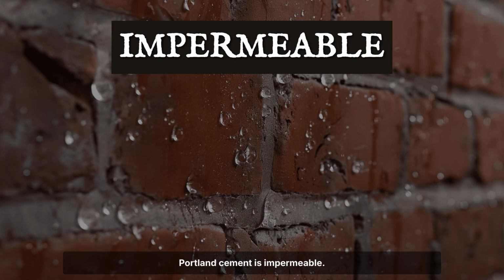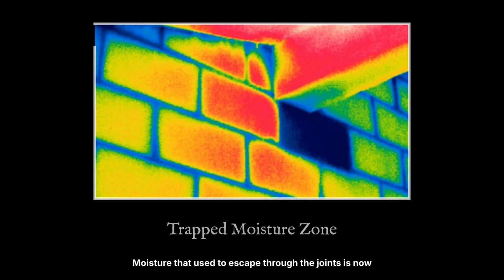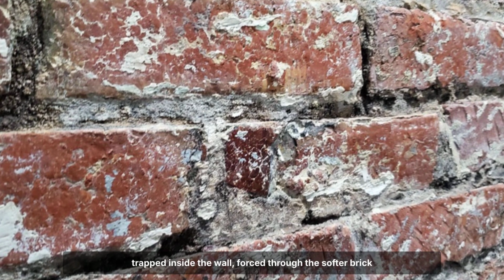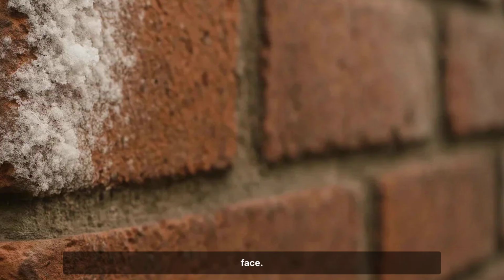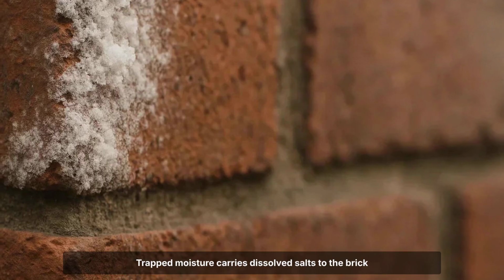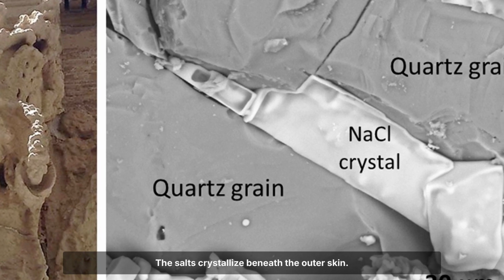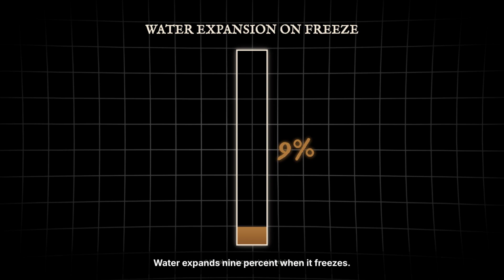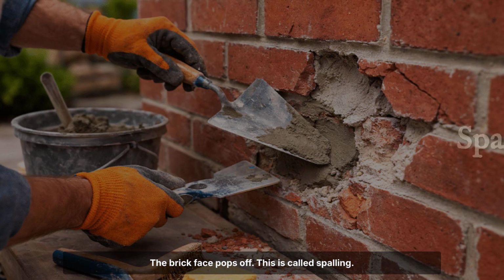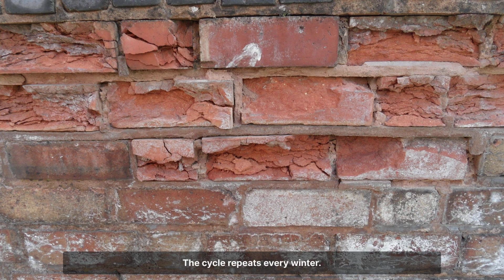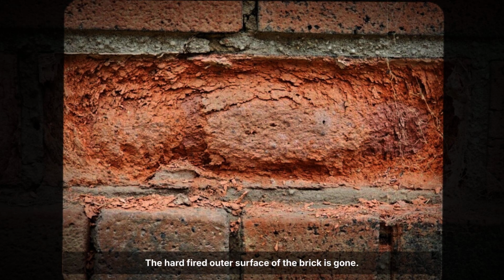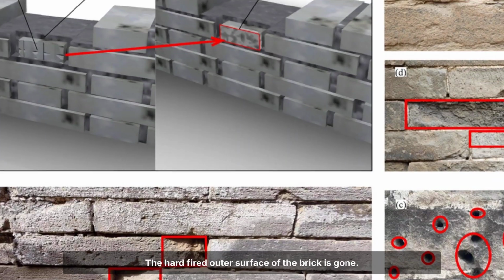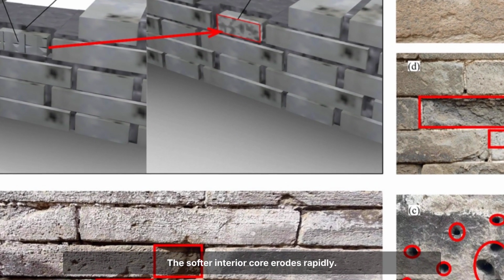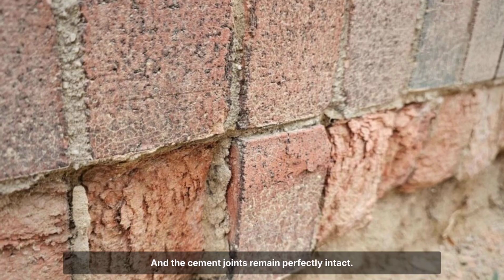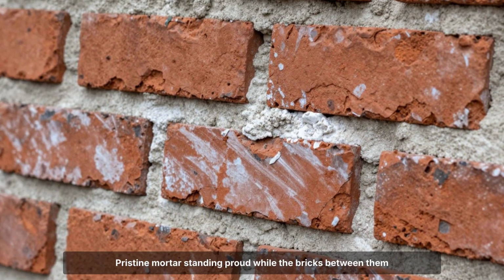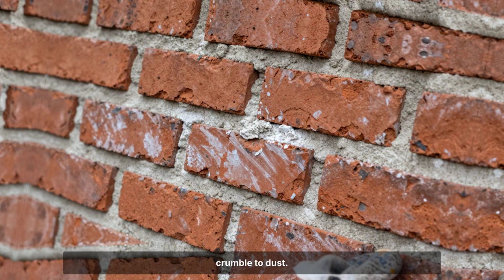Portland cement is impermeable. Moisture that used to escape through the joints is now trapped inside the wall, forced through the softer brick face. Trapped moisture carries dissolved salts to the brick surface. The salts crystallize beneath the outer skin. Water expands 9% when it freezes. The brick face pops off. This is called spalling. The cycle repeats every winter. The hard-fired outer surface of the brick is gone. The softer interior core erodes rapidly, and the cement joints remain perfectly intact. Pristine mortar standing proud, while the bricks between them crumble to dust.